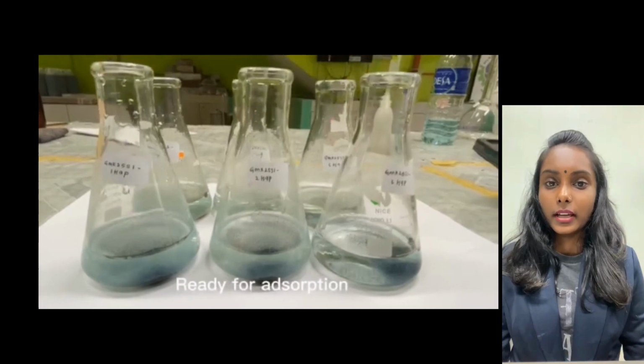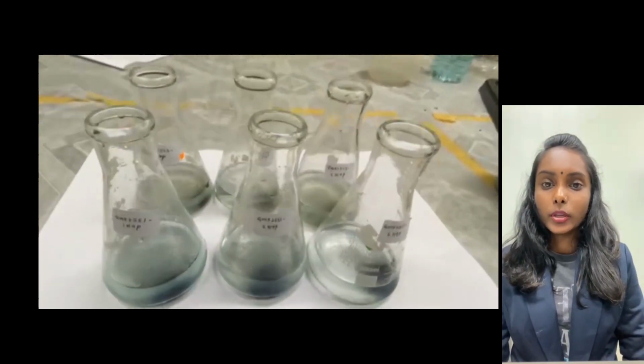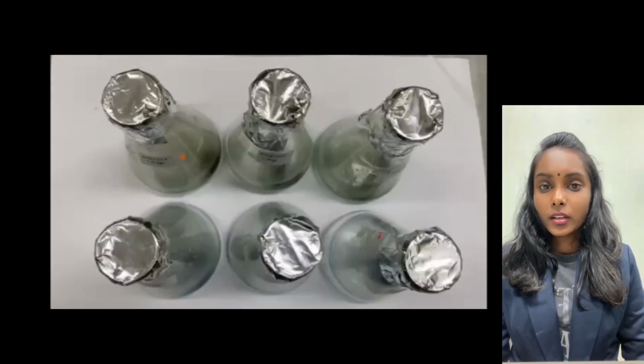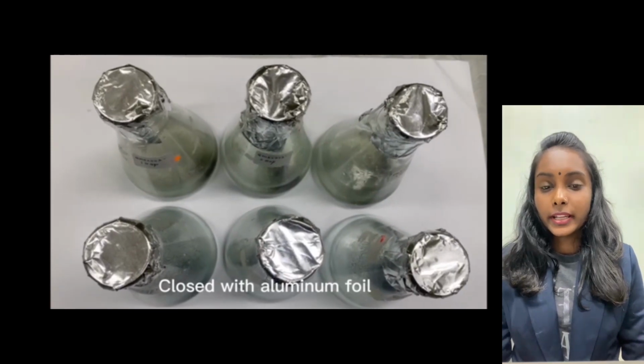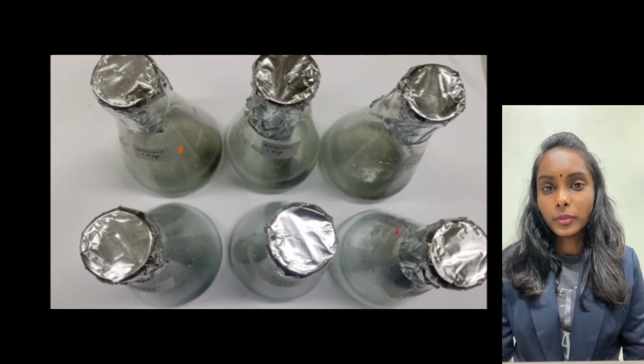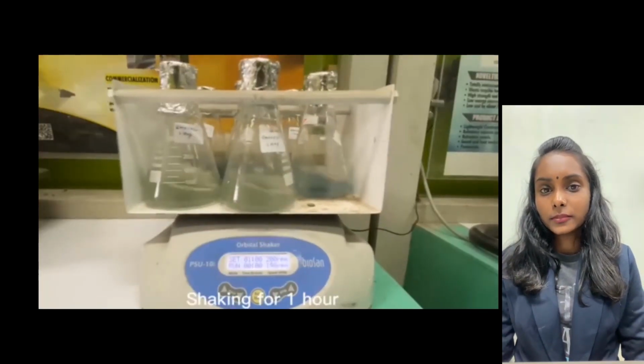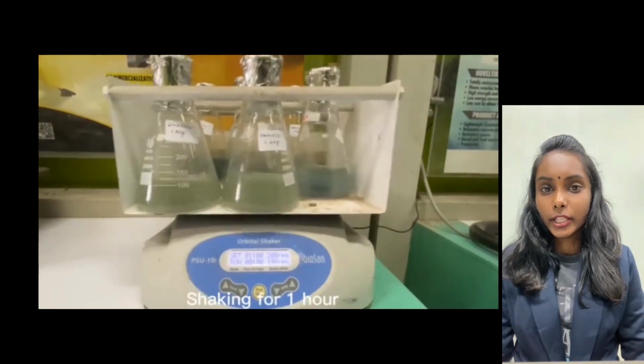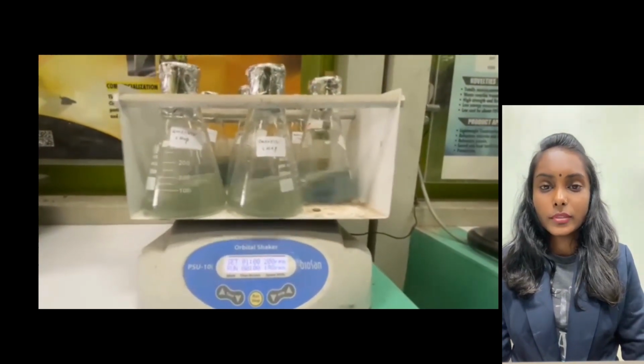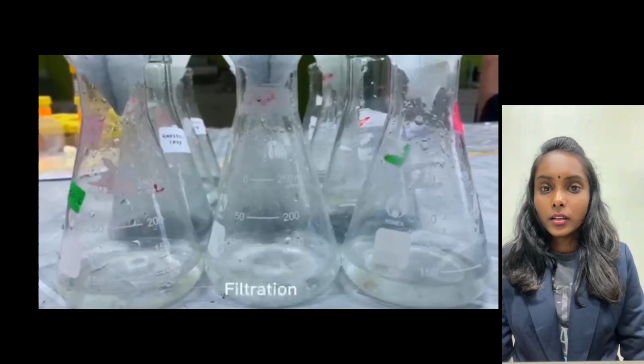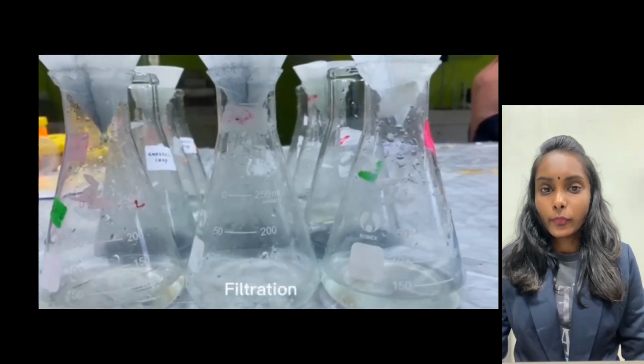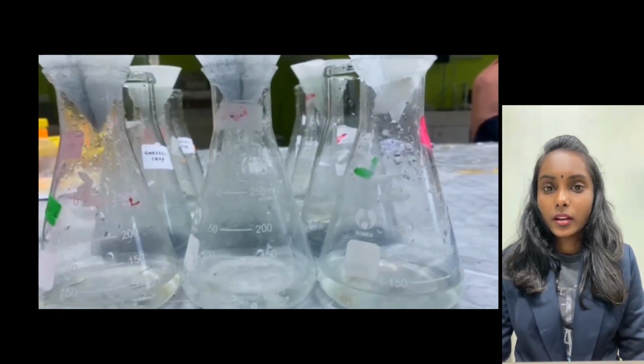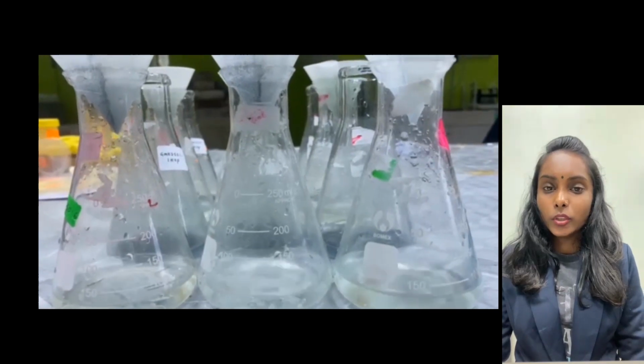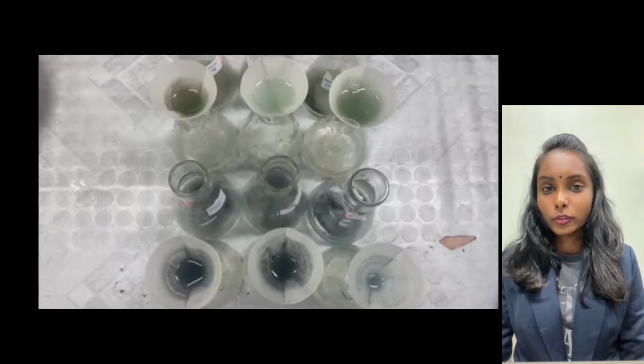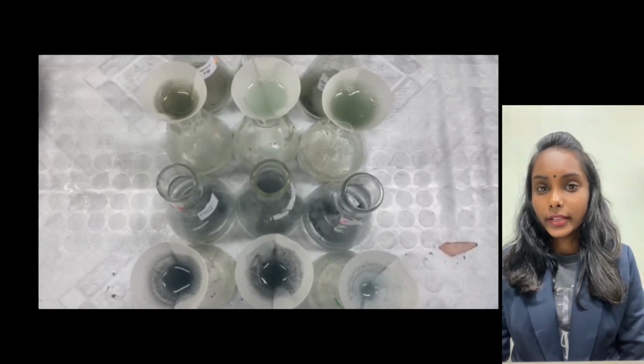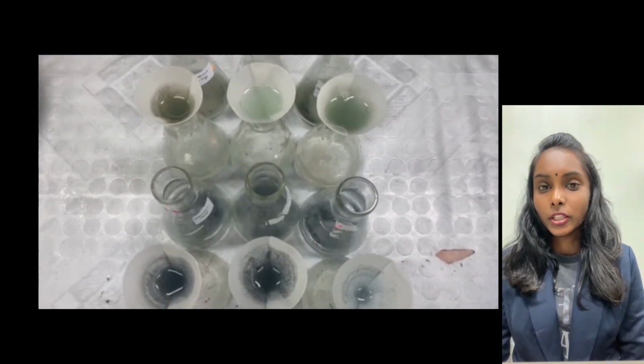The next stage is the adsorption process. During the adsorption process, copper solution with a predetermined amount of adsorbent is placed in a conical flask and then put on a shaker for 1 hour. After 1 hour, it undergoes a filtration process. Then the filtered solution is ready for testing to calculate the removal efficiency of copper.